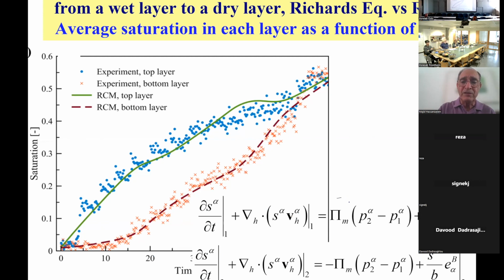I must say we fitted the value of this exchange coefficient. By the way, this exchange coefficient is a property of the space between the two layers, because it tells you that the pressure difference between the two layers is the driving force for exchange of water, and then there is a mass transfer coefficient, and that's a property of the thickness, the space between them. If you push the two layers together, that coefficient will increase. And if they are not pushed against each other, the space is bigger, the coefficient will become smaller.